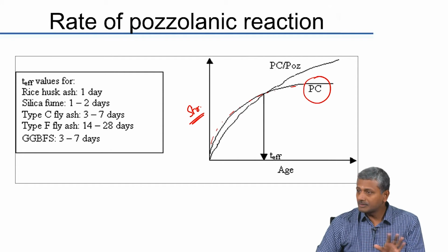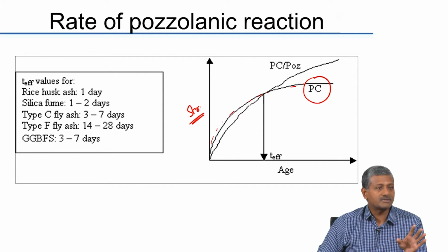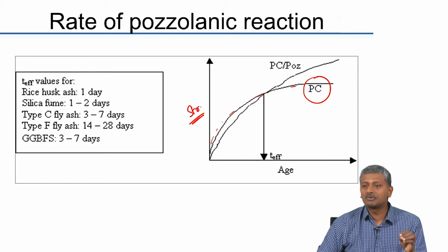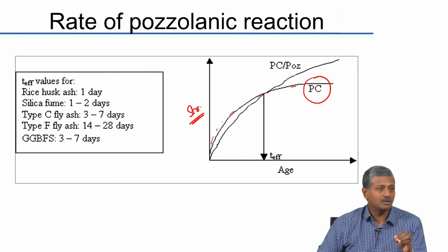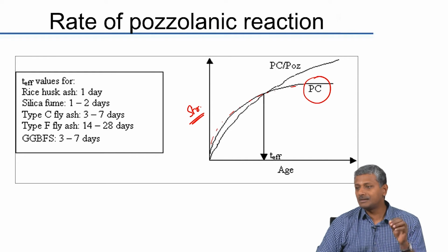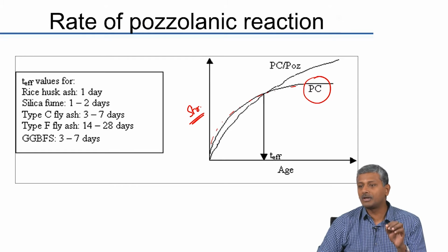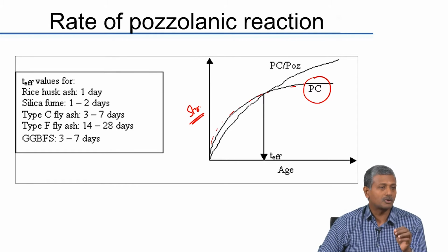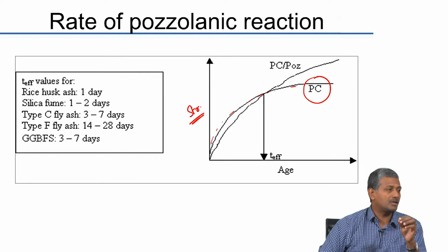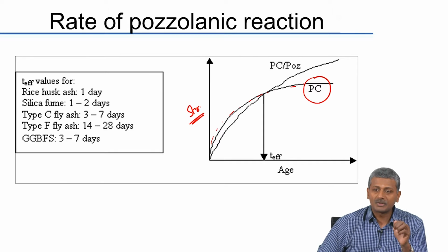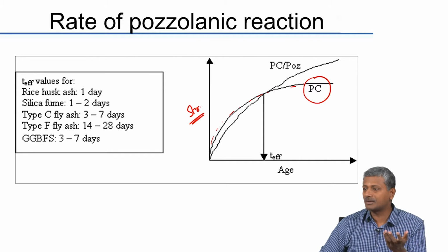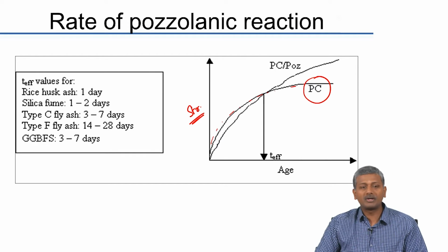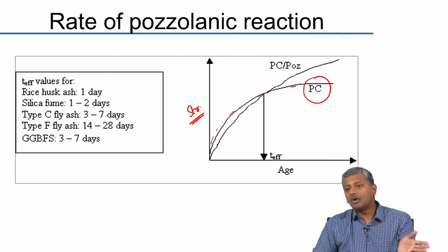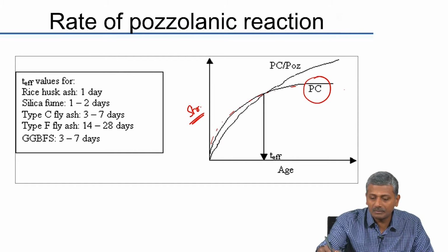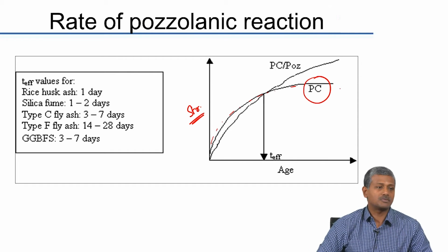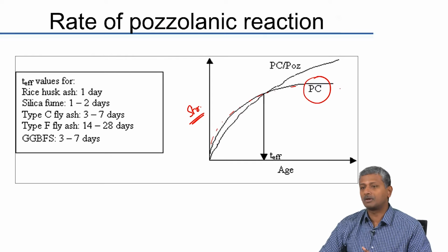But based on our discussion earlier, please remember that curing is very important from the perspective of filling up your porosity, so that you get fewer interconnected voids and you improve the durability of the system. Always please look upon curing as a means of improving durability rather than attaining strength. Without curing you may attain some level of strength, but you will get very poor durability for your concrete. Now, all these continuous strength development patterns are drawn based on the assumption that you are continuing to cure for a long period of time.